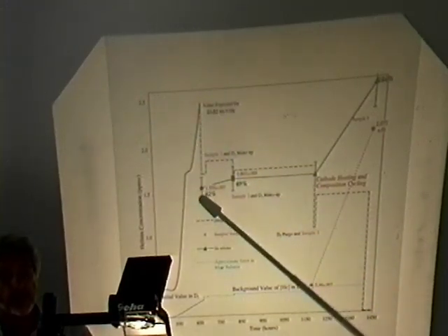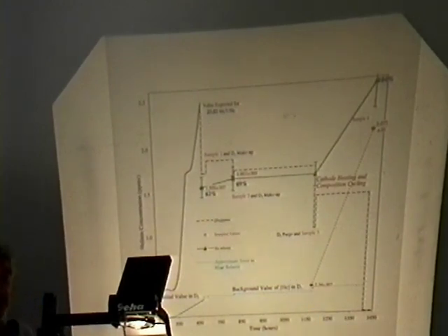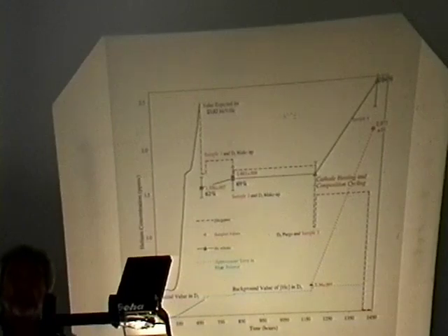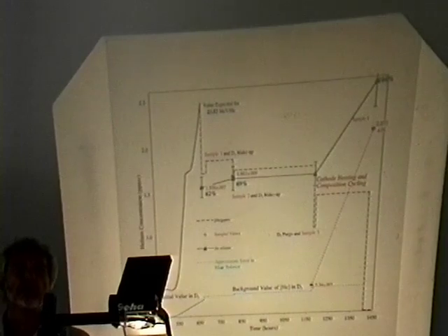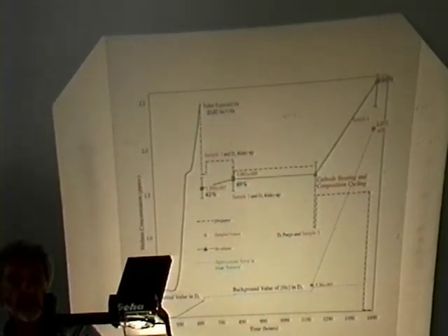What we in fact observed was this point here, which is only 62% of the expectation value. So at the end of this period of excess power production, we had observed a clear increase in the helium-4 signature, but we hadn't got quite as much helium-4 as we had expected, consistent entirely with the results from the two previously described experiments.